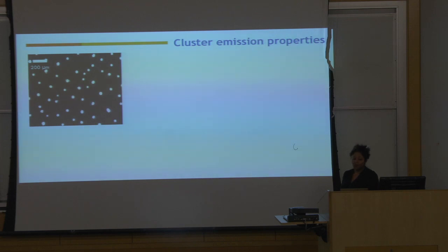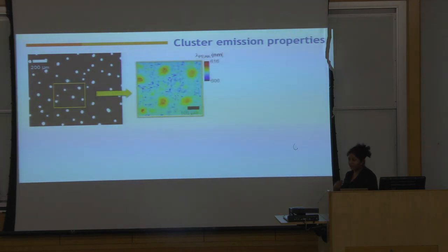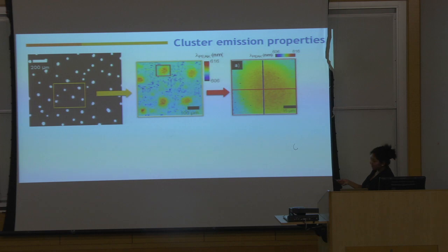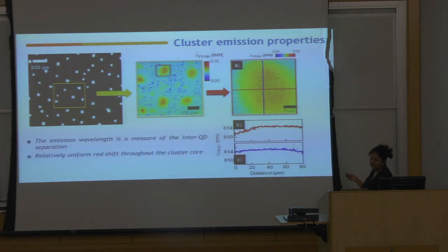But still, let's look at what these clusters actually look like on the optical scale. So we take a small region. We do some scanning PL microscopy here. We are plotting the wavelength of emission of the dots. We look a little bit closer, and here's what we find. In quantum dots, the color is a measure of the interparticle interaction. The redder the color, the more it's a measure of how the quantum dots are exchanging information. If it's very red, or if there is a big gradient, that means there is a big variation.